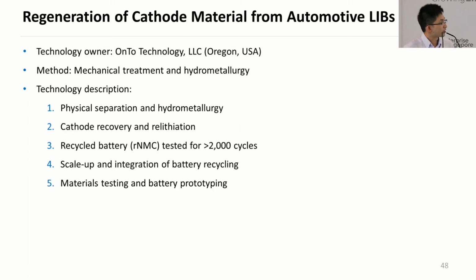So the next one, Onto Technology. They are a US-based company. They focus on physical separation and hydrometallurgy as well. So what they did is they recover the entire cathode material without crushing them, and they soak it in a lithium-rich solution to replenish the depleted chemicals, such as lithium. The recycled NMC batteries, they have tested this for more than 2,000 cycles already, as good as new. And they are able to support the scale-up and integration of battery recycling technologies, in case you are interested. And also material testing and battery prototyping as well.